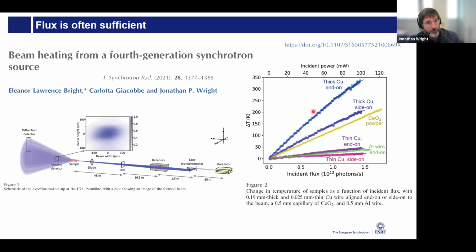This was in monochromatic beam, so we're putting the beam through the monochromator. And as you change the sample geometry and you change the incident flux on the sample, Ellie pulled out the thermal expansion of the sample, which we assumed was due to heating up. So during these experiments, the flux is gradually increasing, and we measured how much the lattice parameter is changing in the sample, and she optimized the geometries to get the minimum possible heating and to increase the heating as much as possible.